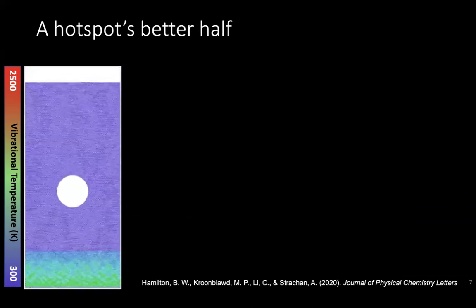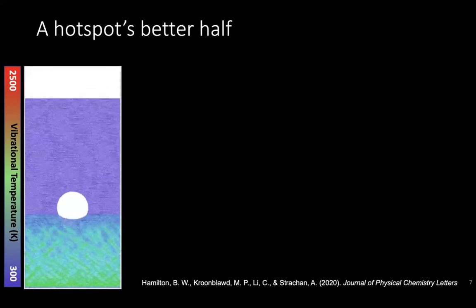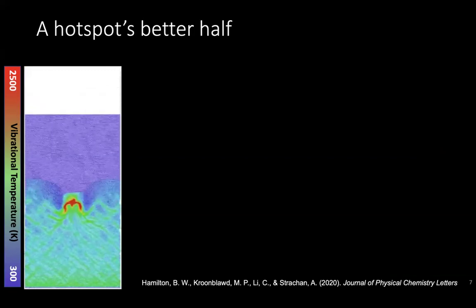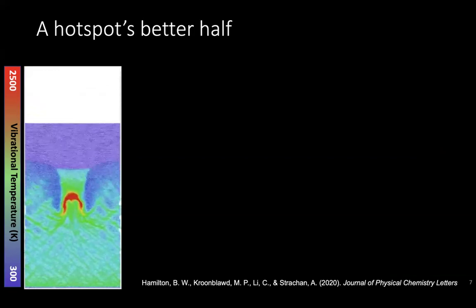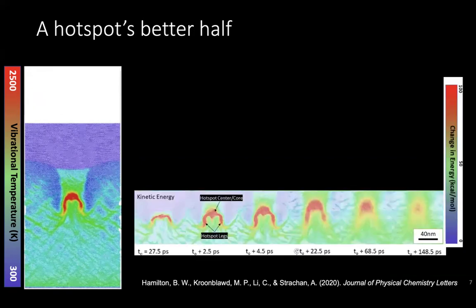So this is a shock just like before, okay, from our center. And we create a hotspot. This is the temperature field, okay? The color is temperature, right? It expands, it recompresses, that's super hot. And so we look at this, and this is a non-reactive simulation. This hotspot wasn't big enough to react, so it dissipates. The temperature dissipates. And for years, we've known about hotspots.